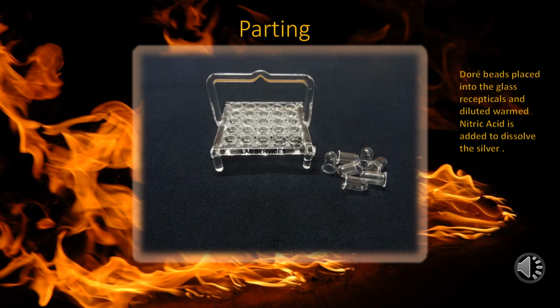After cupellation, the resulting dore bead still requires further processing. The gold and platinum group metals need to be separated from the bead. In other words, the silver and the PGM group of metals need to be parted from the bead. At this point, there are two options available. The first is to part the bead with a slightly warm diluted nitric acid, or if the gold, silver, and platinum group metals are of a low concentration, then dissolvement will be necessary for analytical analysis, meaning concentrations are too small for any physical recovery.